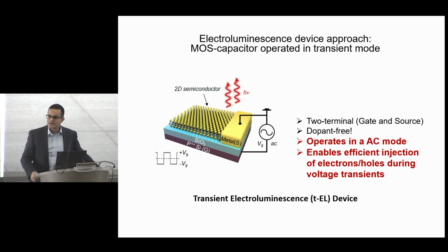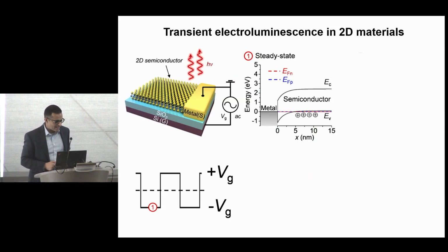So you don't bring in any inversion charges. That's deep depletion. But in the case of monolayers, there is no deep depletion. There is no depletion depth, which I talked about. So in this case, what happens when you flip the voltage really fast between the source and the gate, you can't undergo deep depletion. So the only place where the potential can get dropped at time 0 when you flip the voltage fast is right at the metal semiconductor junction.